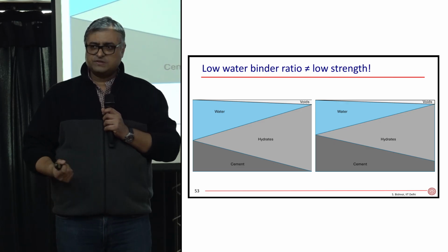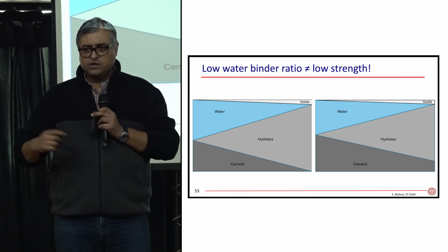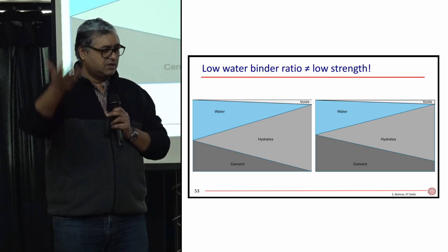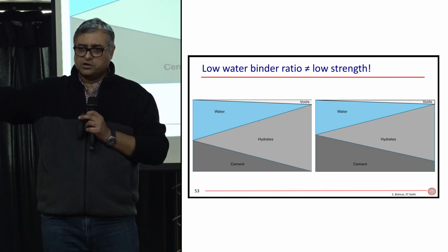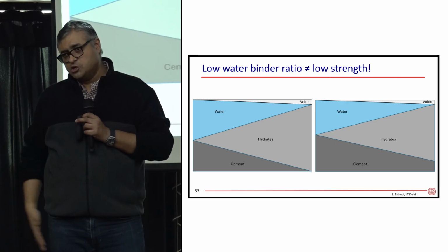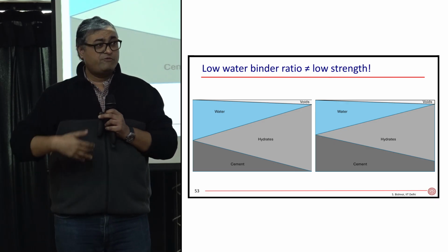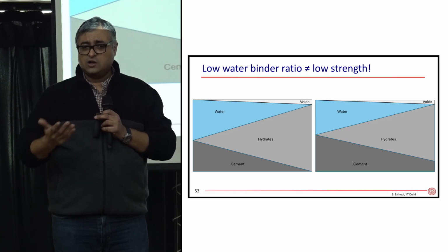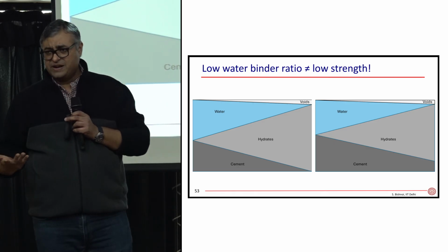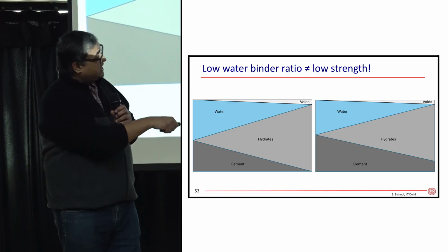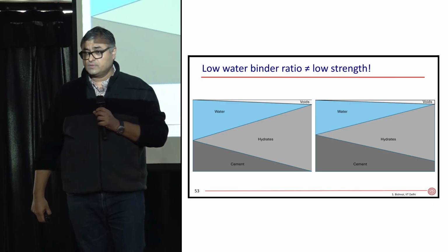Usually, for those of you coming from site practice, where do we use curing membranes? On columns, which have higher strength concrete. They have a lower water binder ratio, so they need more water, more wet curing. What we do instead is seal the concrete. Yes, sealing the concrete is good—it prevents evaporation, but it will not give you the extra water required for hydration, right?